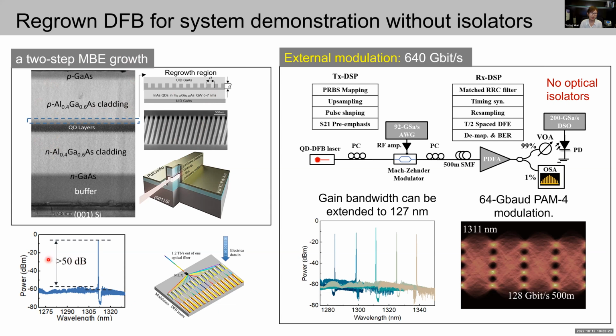So the laser can sustain single mode operation in the ground state across a wide current range of 110 milliamp with a maximal side-mode suppression ratio of more than 50 dB. And the emission wavelengths can cover 1285 nanometer to 1338 nanometer by a laser array on the same chip. And by virtue of the very small alpha factor of quantum dots, we are able to perform the system demonstration without optical isolators. And we got an aggregate transmission capacity of 640 gigabit per second using these 5 channels of the laser array with 64 gigabaud PAM4 modulation.